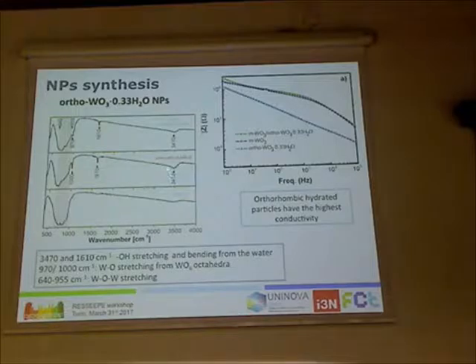I also said that this water inside the particles is important because, as for any electrochemical system, you need to have also some electrical conduction on these materials. So they should not be electrically insulating. Otherwise, as they will receive ions and need to compensate this with also electrons, if they are not conductive enough, this will affect the performance of the device.